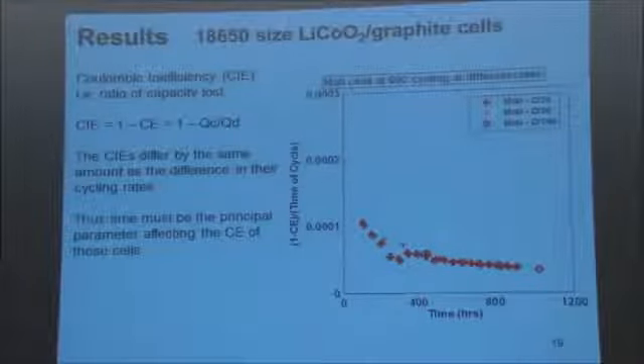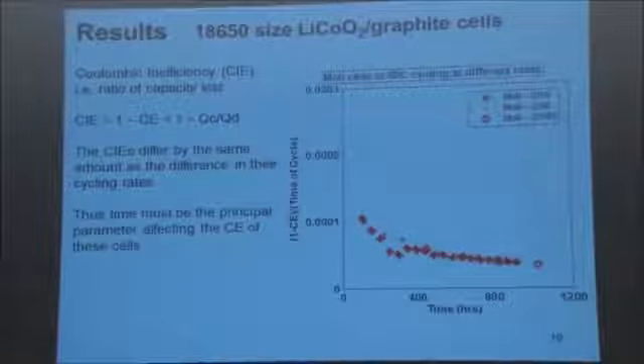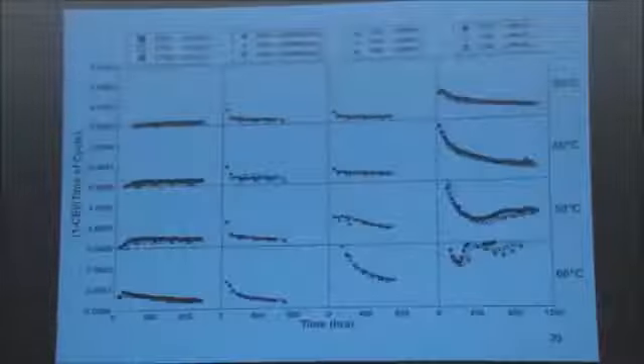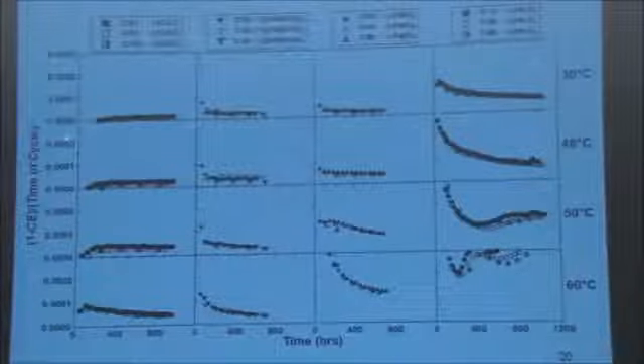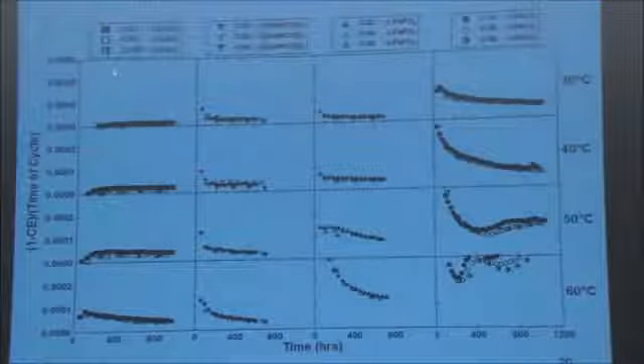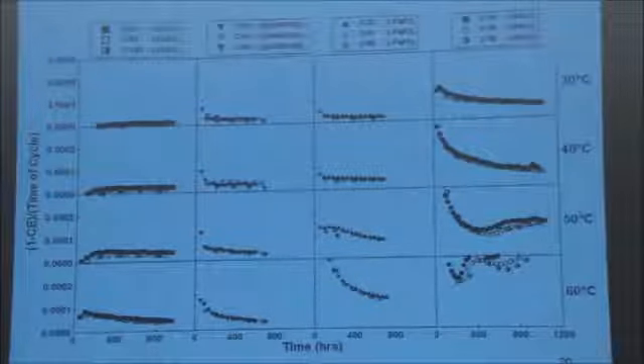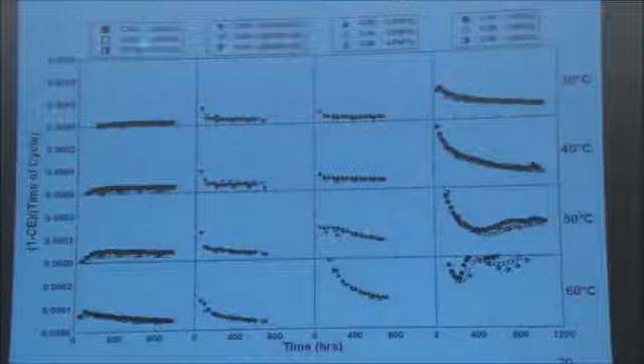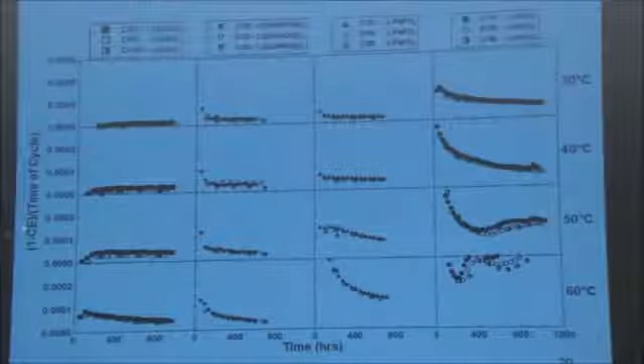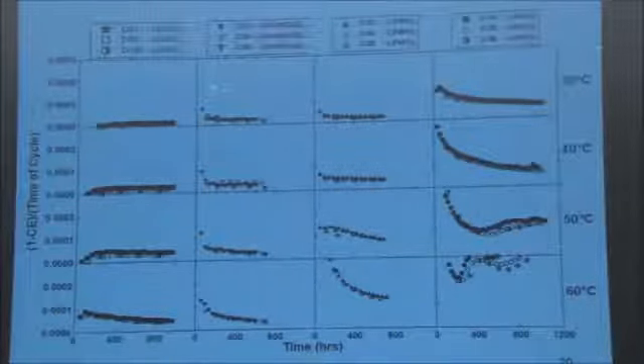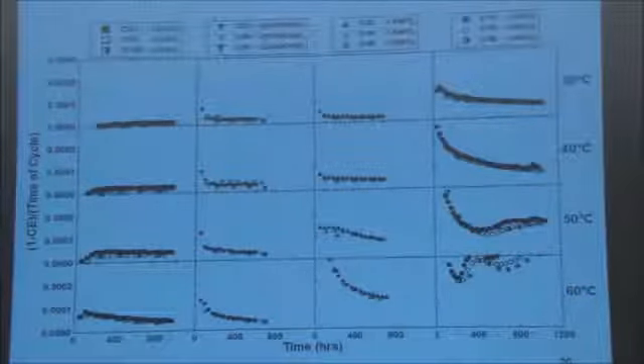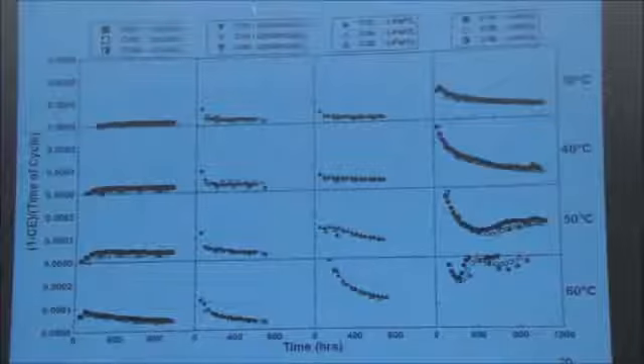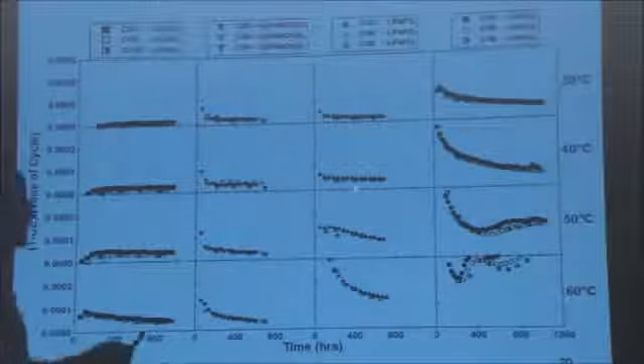And now these measurements can be used to rank all lithium-ion technologies. So I'll just show you some of the measurements. And it's a busy slide, but it's easy to understand once you look at it. Okay, so there's data here for 36 cells. In this panel, lithium cobalt oxide lithium-ion cells running at 3 different rates are being characterized. And it's 1 minus the Coulombic efficiency over the time of a cycle, and it's at 30 degrees C. So as we go from column to column, we change to a nickel cobalt manganese lithium-ion cell, lithium iron phosphate lithium-ion cell, and a lithium manganese oxide lithium-ion cell.